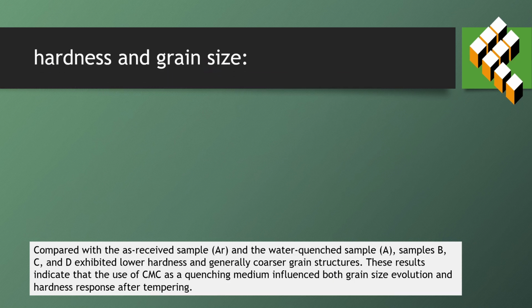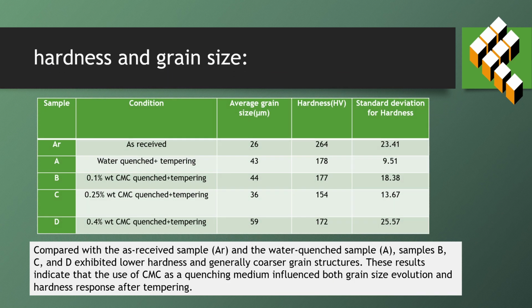Hardness and grain size, as shown in the table, compared with the as received sample and water quench sample. Samples B, C, and D exhibited lower hardness and generally coarser grain structure. These results indicate that the use of CMC as a quenching medium influenced both grain size evolution and hardness response after tempering.